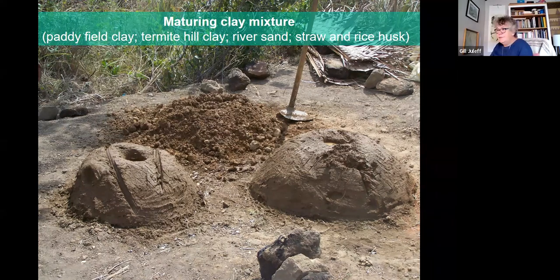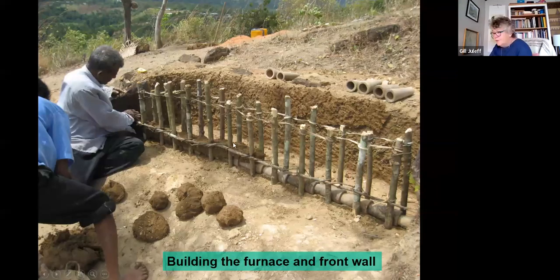So we then built our furnaces. And all of this construction is based on archaeological evidence, apart from the wooden poles that we put in here, because we struggled to get our wet clay wall to stand upright. So we used poles just to help keep it stable, and they burnt out during the smelting. But you can see we have a line of tuyeres here. A local potter made us these pre-fired tuyeres, and the clay that we made is used to construct the furnace. So we're on a known site at a known furnace location.